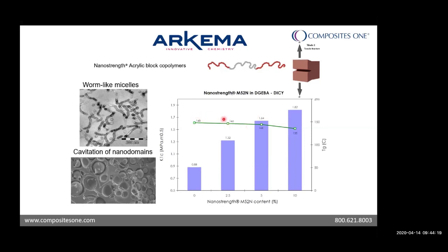And then the green bar represents the glass transition temperature. So even though we've almost doubled the toughness, we've had very little impact on glass transition temperature. And then you could go even farther to a 10% loading and more than double, with still a very minimal impact on glass transition temperature. So you can imagine how this would have a good value proposition for hot, wet environments, downhole applications where you want to increase the toughness of the epoxies without degrading the glass transition temperature.